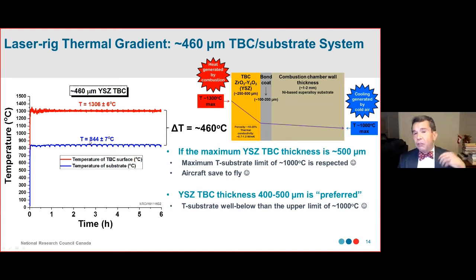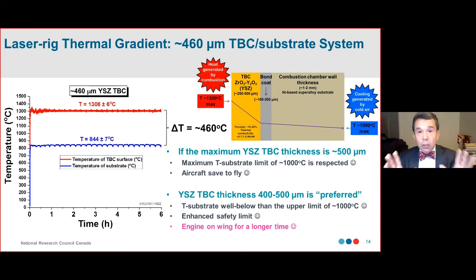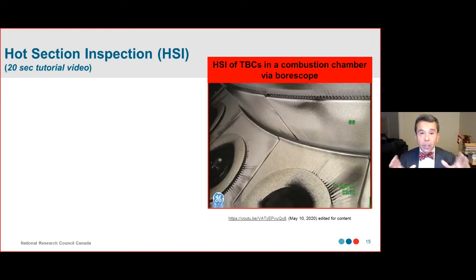And based on that, you can ask why we're not using an 800 micron thick coating. Because even at about 460, we're really protecting the substrate. And if you try to put a much thicker coating like 800 microns, you are basically adding weight to the turbine, and you do not want to do this. So when you have a TBC in which the thickness is about 400 to 500 microns, you have an enhanced safety limit. It means that the turbine is going to be on the wing for a long time, and this is really, really important. And why? For example, I'm going to show a concept called hot section inspection.